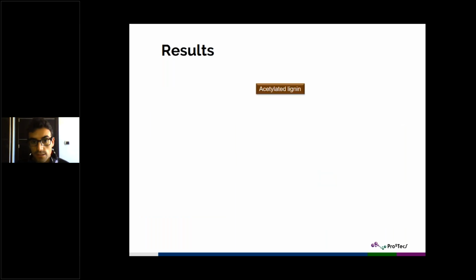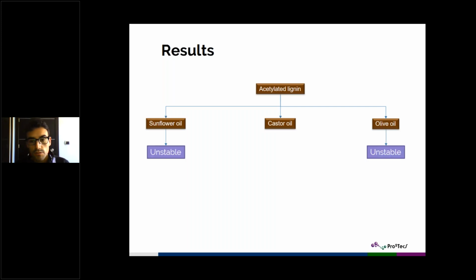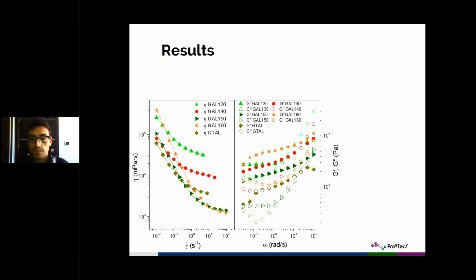Well, so we have the acetylated lignin, and we have tried to mix it with different oils: sunflower oil, olive oil, and castor oil. And what happens is that when we mix the acetylated lignin with sunflower oil and olive oil, we get unstable systems. But when we mix it with castor oil, we get stable systems. So from now on, these properties of the gel are about acetylated lignin plus castor oil mixtures. And now we get the rheological results, both the viscous flow measurement on the left and the viscoelastic functions on the right of the acetylated lignin and castor oil mixtures. Let's go step by step, so you can see all the differences that we have observed.